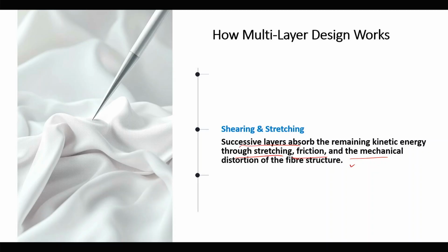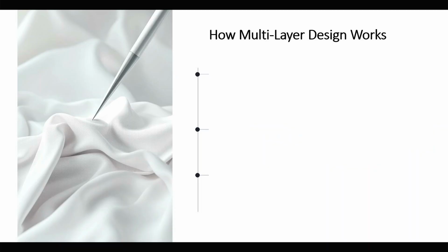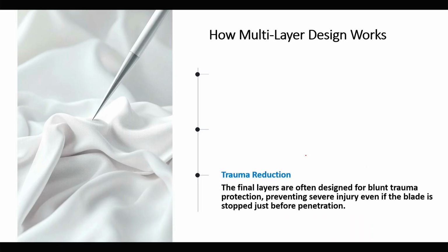Gradually they will absorb the energy, and by absorbing the energy, trauma reduction will be there, so that the person will be protected. The final layer is often designed for blunt trauma protection. After the blunting of the knife, its energy is reduced, and the inner final layer is used for shock absorption, which reduces the blunt trauma, preventing severe injury even if the blade is stopped just before penetration. So, we normally use a multi-layer structure.